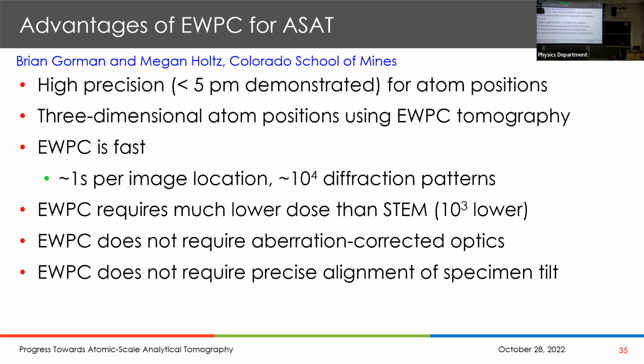And also, you're defocusing to 5 nanometers. You don't need aberration corrected optics for this. So you could do this probably in a very straightforward column, which is not to say you don't need aberration corrected microscopes. If you're thinking about building a combined atom probe and electron microscope, you don't want it to be any more complicated than necessary. So if this is good enough to give us those results in a combined instrument, that is a very attractive way to go.